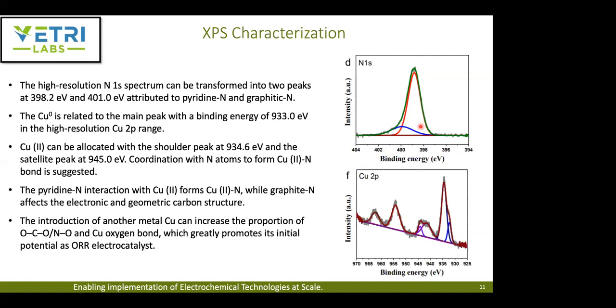And so the pyridinic nitrogen interaction with copper 2+ forms this Cu2+-N. As the graphitic nitrogen affects the electronic and geometric carbon structure. Also, introducing copper metal into this nitrogen-doped carbon structure can increase the proportion of O-C-O bond or an N-O bond. So this actually promotes your initial onset potential. So that is a good characteristic of an overall catalyst.